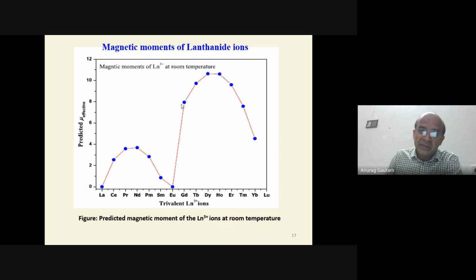that is not an overall measurement, but that change gives how fast the water comes to the surface of the particle and gets relaxed. That is also called the residence time. So this is why it is a T1 contrast: because of the residence time. If the water is coming onto the surface, it should go away, not hang up there. And T2 is the overall measurement. The residence time on the surface of this is very short. That's why, I think, with a large number of unpaired electrons, which is 7, gadolinium is used as a T1 contrast agent.